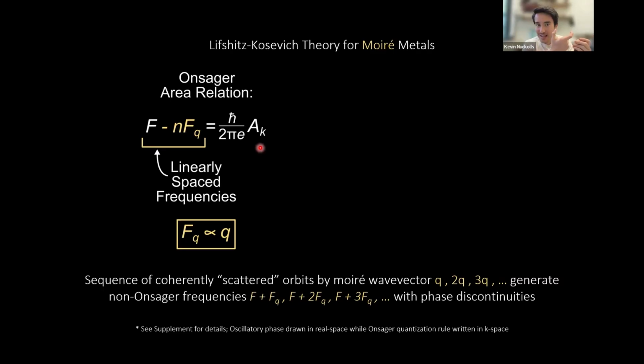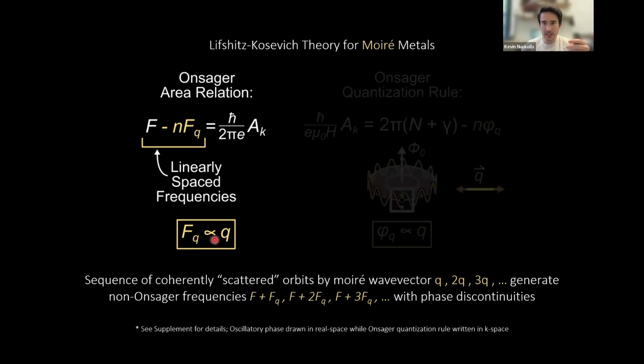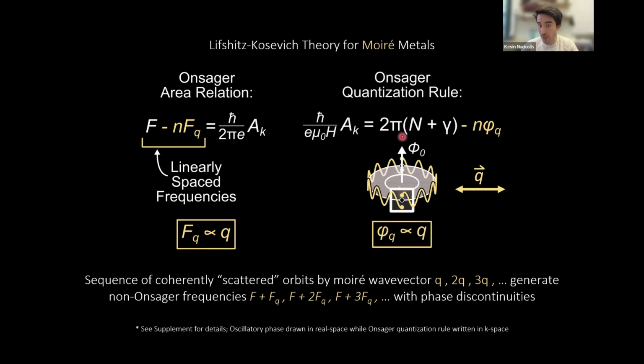But when Q is finite, then each frequency in the Fourier transform of the unmodulated metal will split into a sequence of frequencies set by the Moiré wavelength. Indeed, Onsager's quantization rule also gets affected by phase discontinuities, such that when we complete this orbit, we're no longer 2 pi periodic, but we're 2 pi periodic with an extra phase discontinuity.